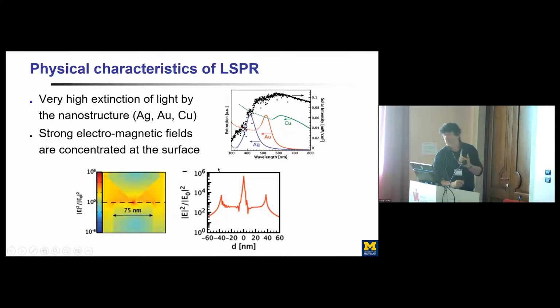A major characteristic of this surface plasmon resonance condition is that you're actually concentrating the energy of the light that's interacting with this system at the surface of the nanoparticle. So here I show the intensity of the electric field associated with a combination of two silver nanoparticles, two cubes of silver positioned 45 degrees with respect to each other as they're interacting with light. And you can see that this electric field is dramatically enhanced compared to the field of the incoming light.